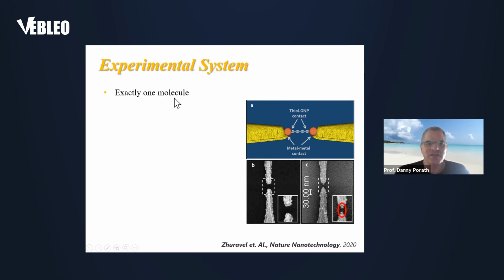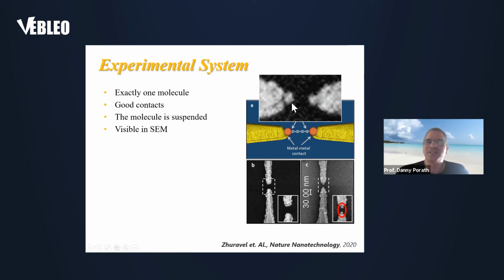So we have, as we asked before, just one molecule. We have good contacts. The molecule is suspended, so there's no contact with the surface. We can see that the dimer is there, so that's an additional way to verify that a single molecule is there, as we showed by the preparation and separation by the gel. And indeed, we have high experimental confidence. The price is that the statistics of current voltage is much smaller than, for example, in STM break junctions, where you can measure thousands of curves again and again on many different molecules.